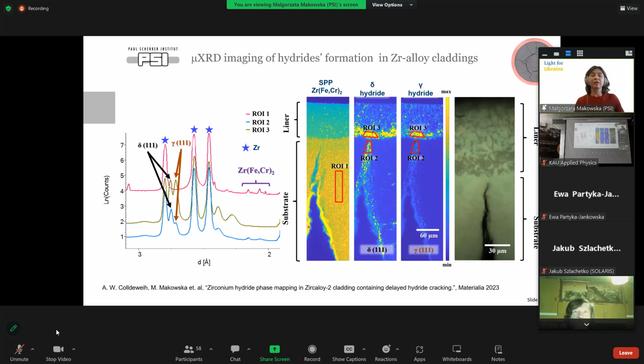We could also, based on fluorescence, see differences between two different parts of the alloy. I am not going into the details of it, but here we could see that we have two different alloys, and the difference we could see essentially based on fluorescence and diffraction contrast. And thanks to this, we could see that at the edge of these two alloys, we have formation of hydrides in high concentration. So we could see that these hydrides are agglomerated at this edge, but also at the tip of the crack. The interesting thing is that the stress induces formation of the hydrides. And on the other hand, the hydrides are very brittle, which accelerates the formation of the crack itself.